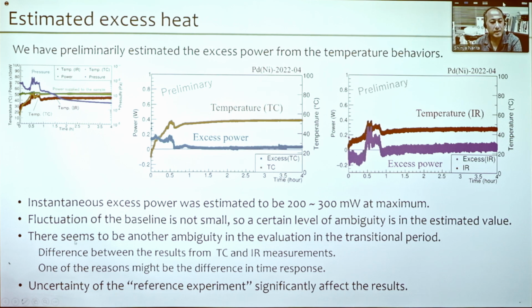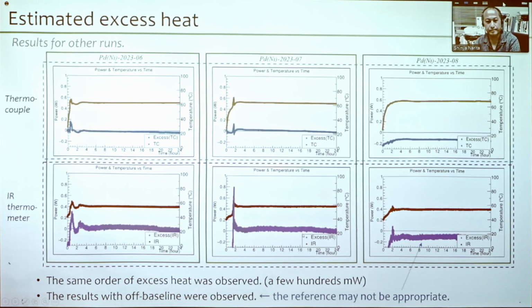And there seems to be another ambiguity in the evaluation in the transitional period, so the difference between the results from the thermocouple and the infrared thermometer results. So, as I mentioned before, one of the reasons might be the difference in the time response. And also, we should keep in mind the uncertainty of the reference experiment significantly affects that result. So we should look carefully at the reference result.